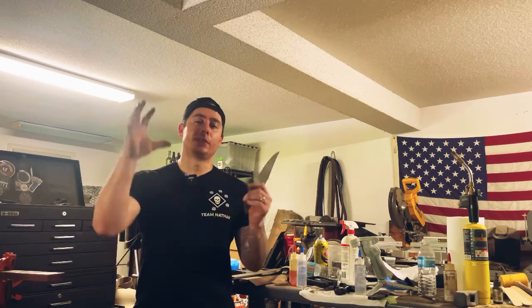And what that's doing is it's shrinking that grain, and then it's holding that grain where it is. I heat it back up to 1500, it shrinks that grain a little more, holds it. Once it goes to room temperature, shrink that grain again on that third time, and it's good, right? And then after that, we do the quench. So 3 normalizing cycles, heat it back up, and then you do the quench.